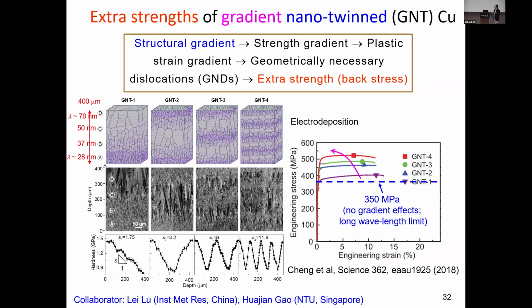In this tensile stress-strain curve, we can see that as we increase the structural gradient, we can increase the stress. So the structural gradient can cause a strength gradient, right? The thin twin layers give us a high strength, while the thick twin layers give us a low strength. We have a strength gradient through the sample thickness. So as we apply the horizontal load, the soft region yields first, producing larger plastic strain, while the hard region yields later and produces smaller plastic strain.